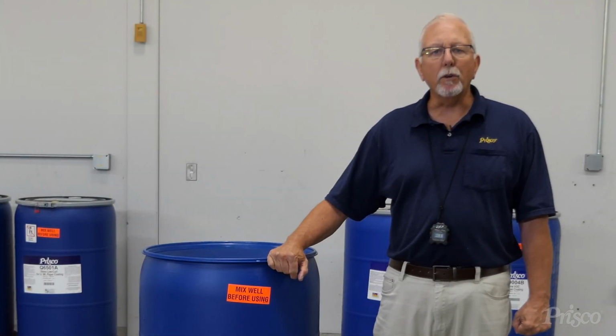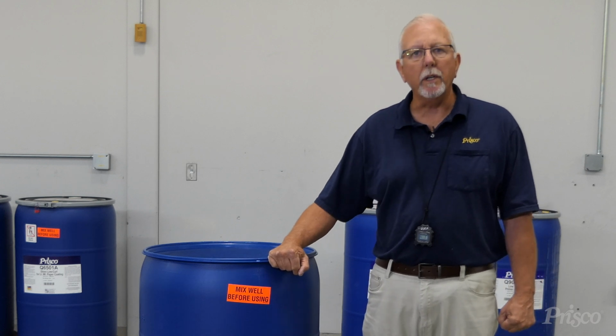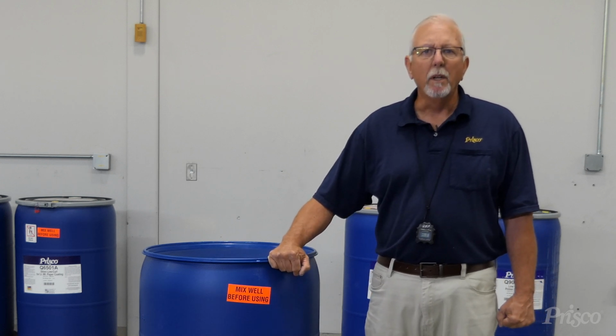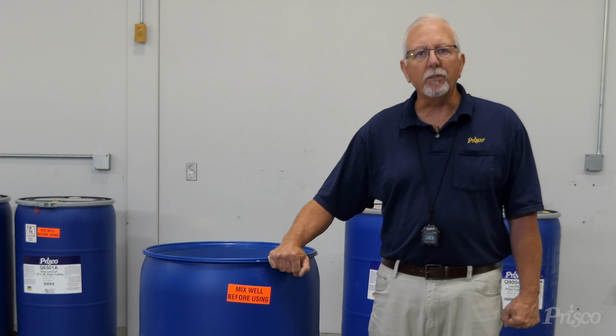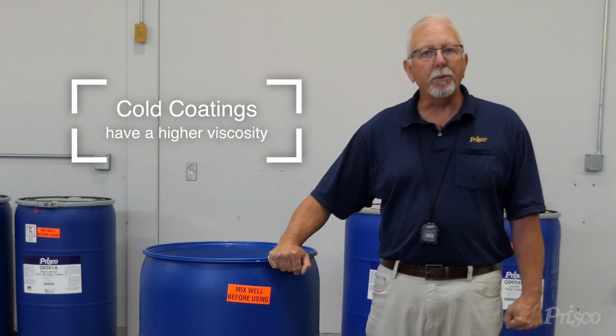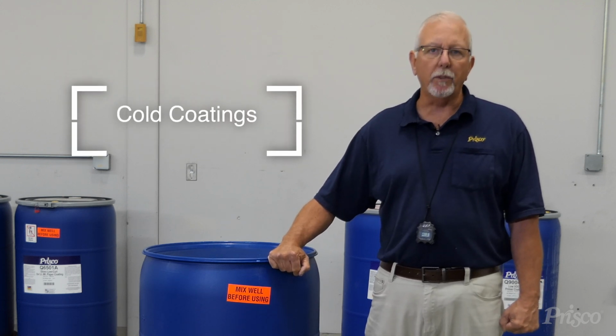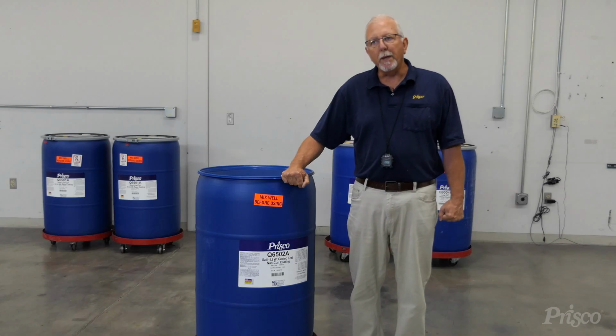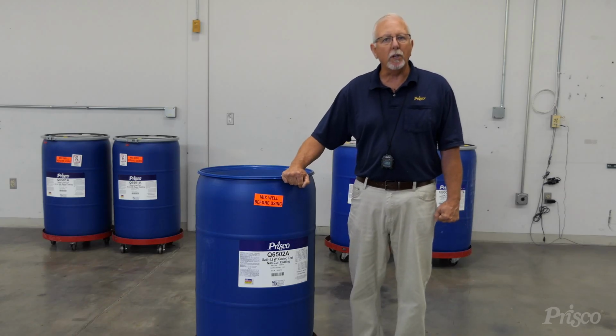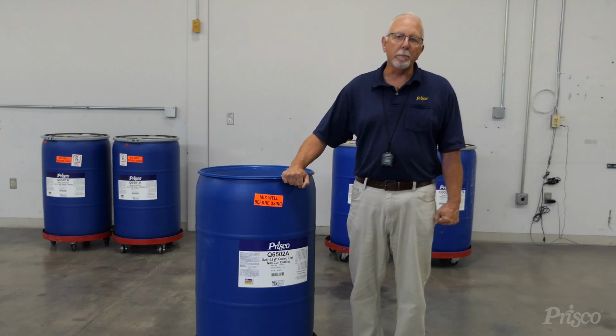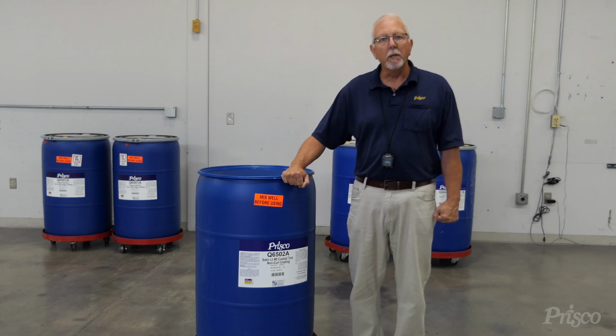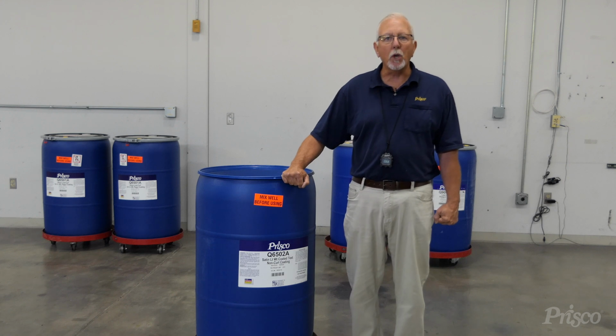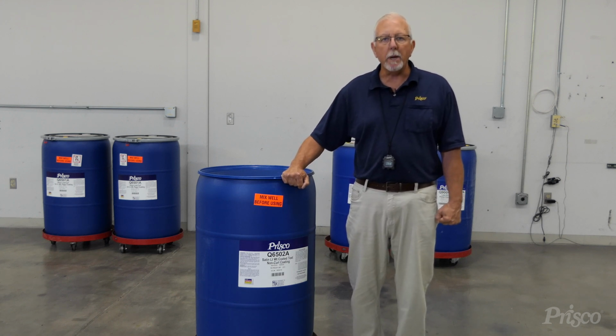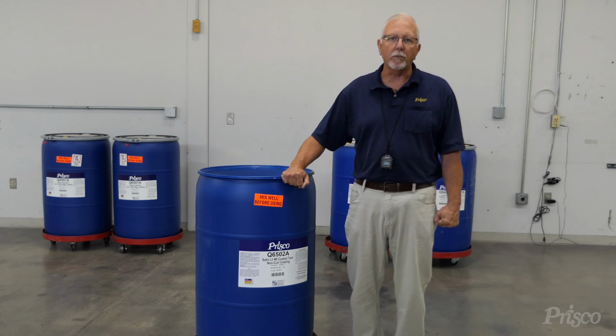Some common mistakes that are made in the press room concerning coating, especially in the winter time, they'll bring a drum of coating to the press that's 60 degrees, and they'll throw it on press without checking the viscosity or the temperature. They might end up running 10,000 sheets and the coating is out of spec. They might have some drying issues at that time and wonder what's going on. So make sure that when you bring a drum of coating to the press room, that you let it acclimate to temperature before you make any kind of adjustments or put it on press.